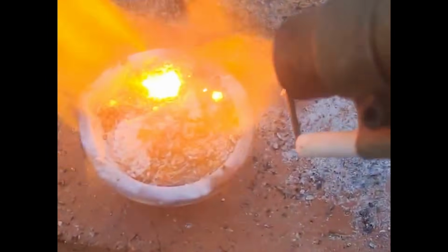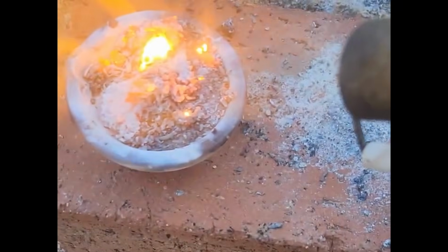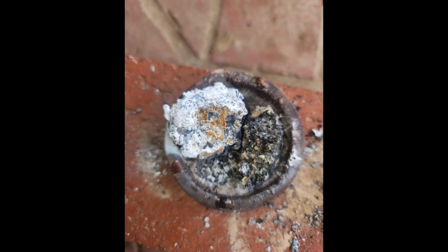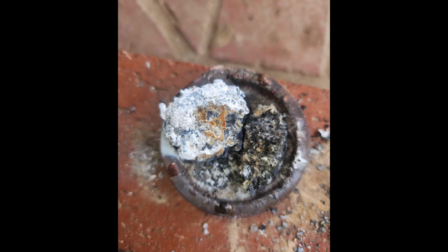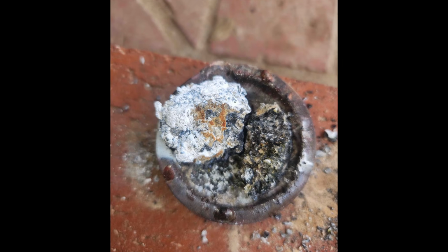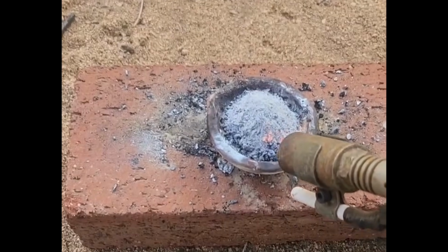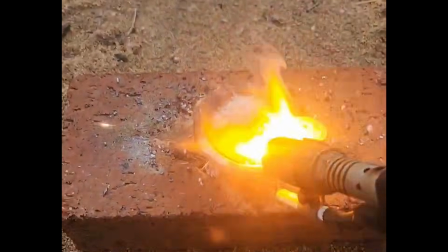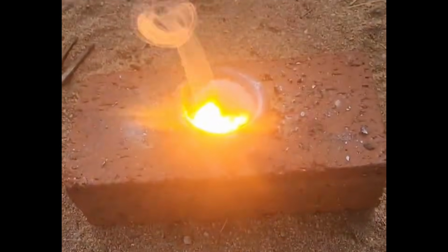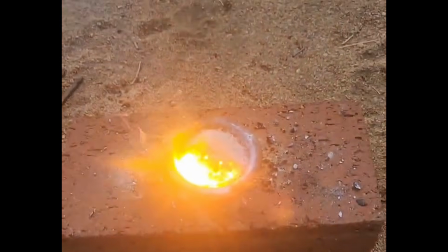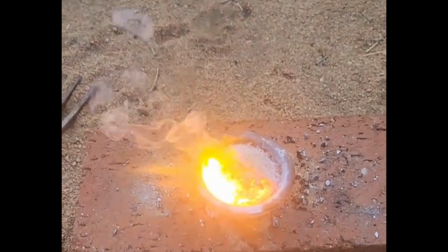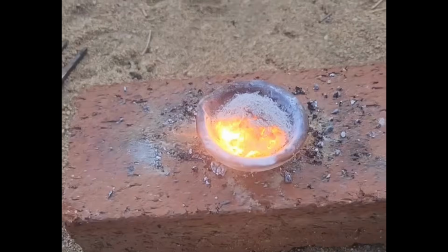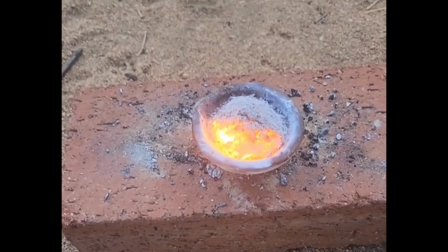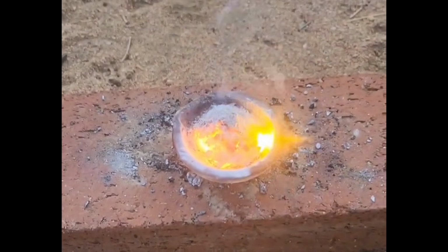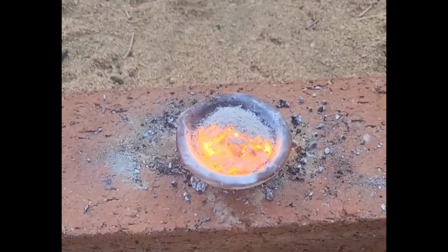But if you reduce regolith with calcium first, then you have all the oxygen in calcium oxide, and then you should be able to yield close to 100% of the oxygen from the calcium oxide. And it gets even better because this calcium redox reaction, again similar to a thermite reaction, should itself generate a ton of thermal energy, essentially preheating your regolith before sublimation. And it might even sublimate some stuff on its own at this step, which may actually be a problem, but one I'm sure can be managed and is definitely worth the free thermal energy.